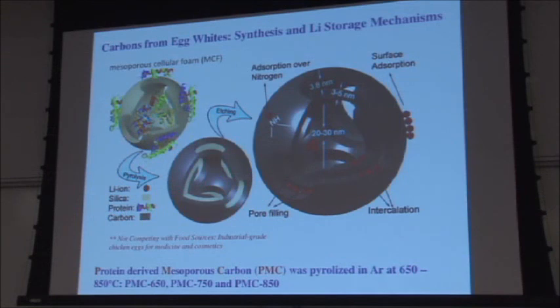He took the egg white, extracted the proteins, inserted them into these mesoporous cellular foams that he synthesized, carbonized the whole thing, dissolved the mesoporous cellular foam, and got a bimodal microstructure where you have one set of pores that are 20 to 30 nanometers in diameter, corresponding to the diameter of these cells, and a two-dimensional tubular porosity corresponding to the thickness of these foams, so basically 3 to 5 nanometers.